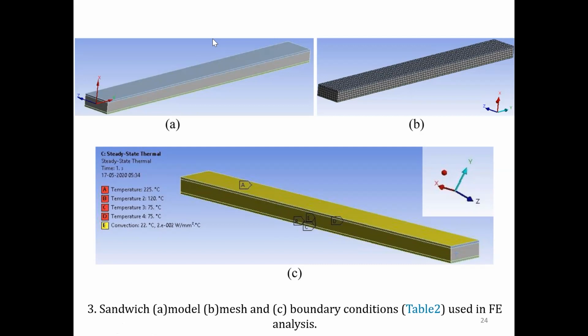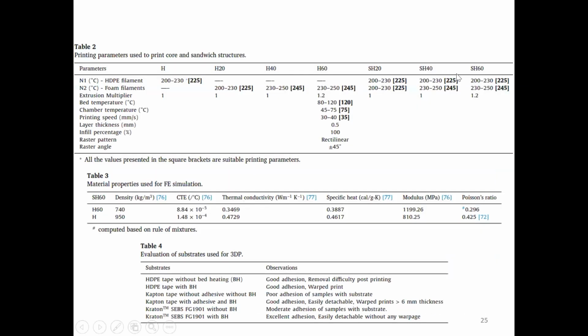Figure 3A here and 3B present the sandwich finite element model and the mesh respectively. The convection boundary conditions are imposed, as you can see in figure 3C here, and the subsequent analysis was carried out for temperature distribution, and then the obtained temperature data is taken as a load data for static structural analysis. To reiterate, this is just to observe a stress distribution in 3D printed samples. So the pilot investigations are carried out using these actual range of temperatures which we utilized for the 3D printing.